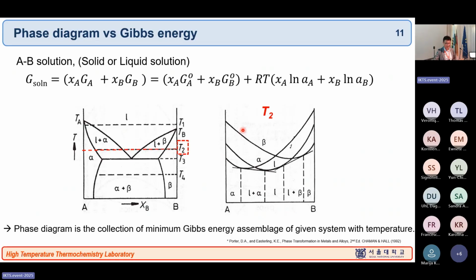Let's assume I have alpha phase, beta phase, and liquid phase. If I know the Gibbs energy of this one with the composition, then I can draw the Gibbs energy like this. And then at each composition here, at the given temperature, we want to know what's the equilibrium phase. Okay, the chemical reaction. Which phase is more stable? Here at the bottom, you can see that alpha phase is more stable, and here liquid phase and beta phase. And when you see here, because of the cotangent line, we can have the minimum Gibbs energy by combining the alpha and the liquid phase, which makes a lower energy than pure alpha or pure liquid. So that's why we can have a two-phase region here. Okay, so if we represent all these equilibrium compositions in the diagram, then we can make a phase diagram.